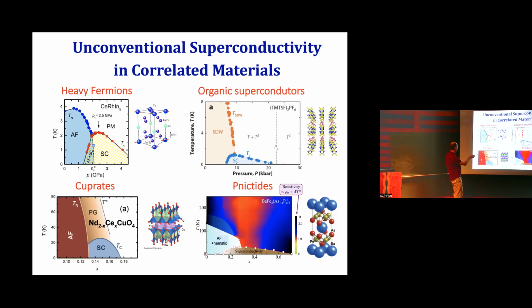You always get superconductivity in some range of parameters next to some other non-superconducting but symmetry broken phase. It may be a competing phase, maybe its mechanism is related to that of superconductivity, but it's always some kind of magnetically ordered state. And our understanding is that this magnetically ordered state is coming basically from the same electron-electron interactions. Then it either competes or cooperates with superconductivity. But this is the type of phase diagram we would expect for such unconventional superconductors.